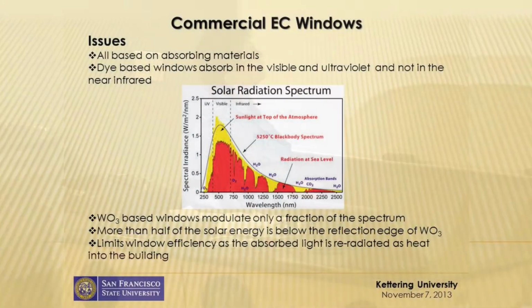Now, commercial EC windows, what are the issues based on? Those devices are all based on absorbing materials. Dye-based windows absorb in the visible and ultraviolet, but not in the near infrared. This is the typical solar radiation spectrum for those devices. Tungsten oxide-based windows modulate only a fraction of the spectrum. More than half of the solar energy is below the reflection edge of the tungsten oxide layer. So that limits the window efficiency, and absorbed light is re-radiated as heat into the building.